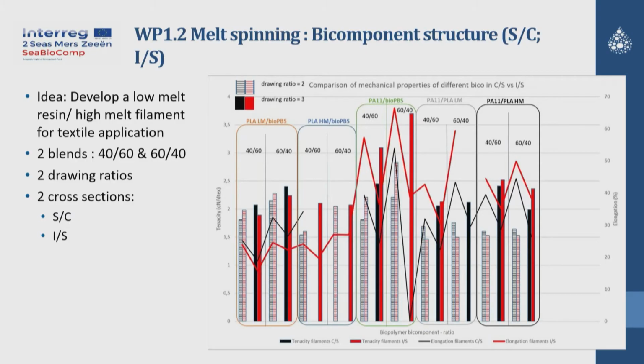We focused first on high melts and low melts, but after making this study, we tried to mix different polymers which can be considered as high melt or low melt polymers. So we tried different ratios, 40-60, 60-40. You have the results here in terms of tenacity and elongation. It's complex graphics, of course, but you can see the tendency.